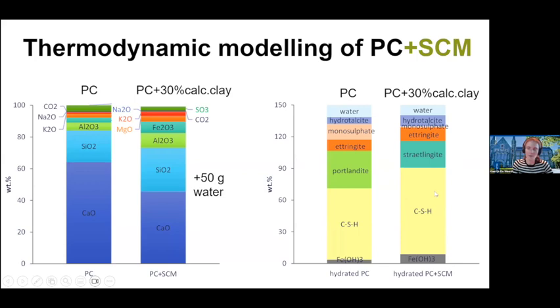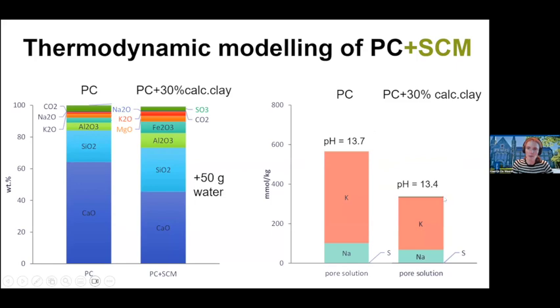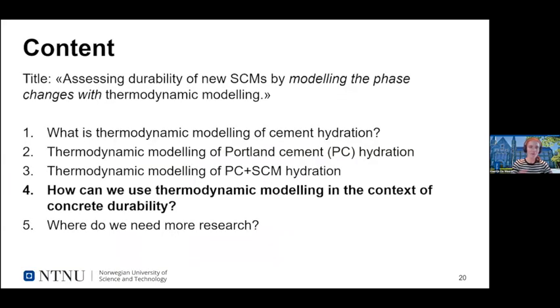And it doesn't only affect the solids, it also affects your pore solution composition. So when we compare the pore solution compositions, we can see that the calcined clay considerably reduces the potassium and sodium in your pore solution, and thereby also the pH of your pore solution. So these are also things you can use SCMs for, to calculate how that would change depending on your SCM. So this was a very fast crash course on how we use SCMs to look at hydration and how we can see how SCMs affect our hydrate assemblage.